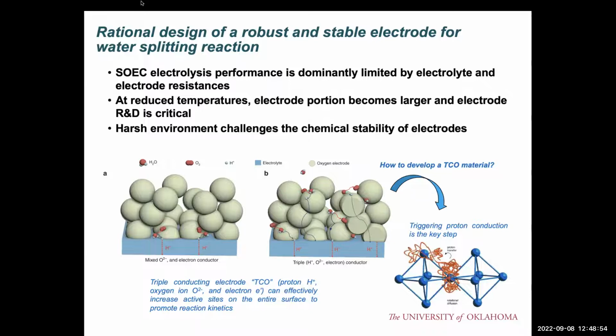But if we can extend the conductivity to three-phase conductivity, which is the oxygen ion, proton, and also the electrons, we can easily extend the reaction active site from the interface to the entire electrode surface. As Figure A is showing, for the mixed conducting electrode, the reaction is just limited to an interface. But if we can develop a material which can conduct these three charge carriers, we can easily facilitate the increase